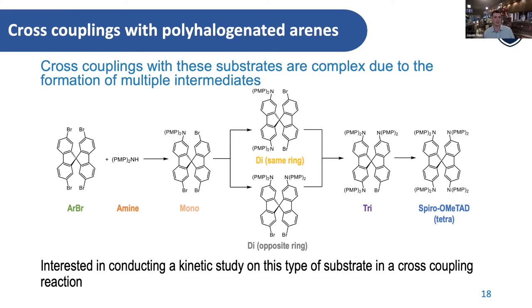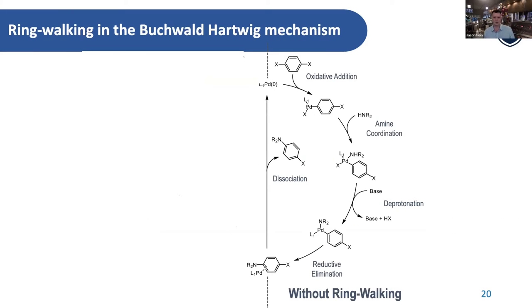So it's already a very complicated potential intermediate. And understanding how it moves through these cycles was key to really optimizing the kinetics and just getting the reaction to work cleanly. So what we found, though, was a really interesting phenomenon. Although you can abstract and say each one of these CN events is a different reaction, so I'm going to do an oxidative addition of my palladium onto that site, I will then coordinate my amine, I will do my deprotonation and then a reductive elimination.